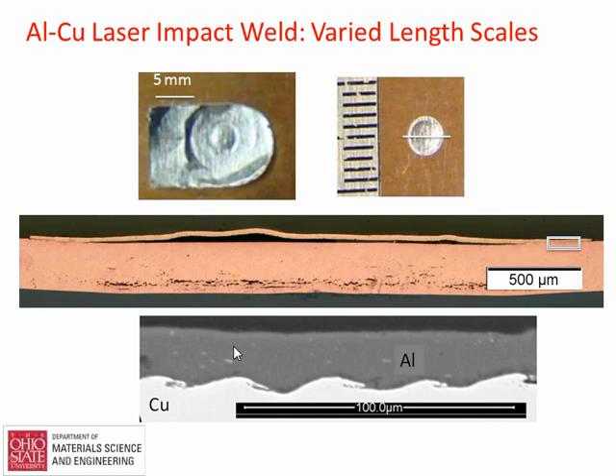right where the laser launches the flyer piece, there's flat impact or non-oblique impact, so no welding occurs in that particular region, but there's welding which happens around that region wherever the velocities and the angles become optimal and come within that welding window that we talked about earlier. Typical waves are observed. The wavelengths and the amplitudes of these waves are different than the larger scale processes, and this is something that is undergoing study right now.